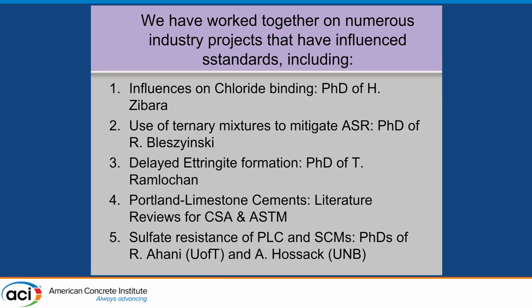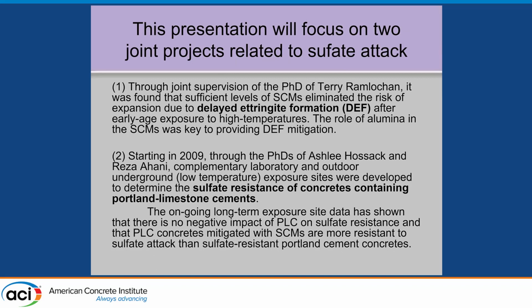So I'm going to talk again, as I mentioned, about the 2 projects. One of them is the PhD. We jointly supervised a PhD of Terry Ramlochan. Unfortunately, Terrence died of heart failure about 10 years ago now. But it was an amazing piece of work where we discovered that sufficient levels of SCMs eliminated the risk due to DEF, and he found out why that worked. And the role of alumina in SCMs was key to providing that mitigation.